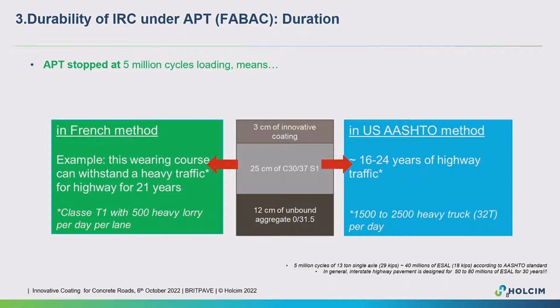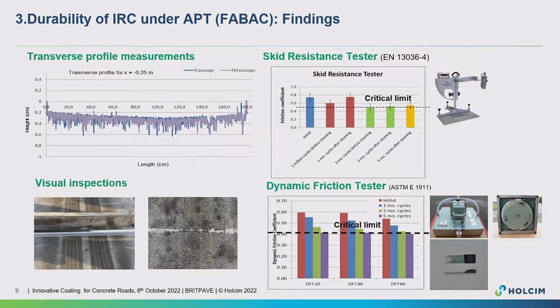And then we carry out the monitoring program during this 5 million cycle loading. The first one is a visual inspection, so we didn't observe any rutting damage on the surface, even on the joint areas. With the transverse profile measurement, there is no difference between the initial and the finished status.